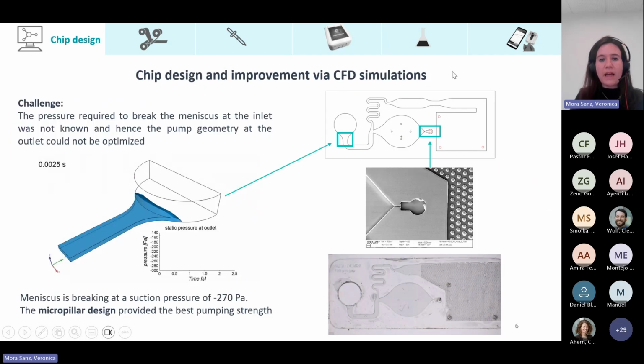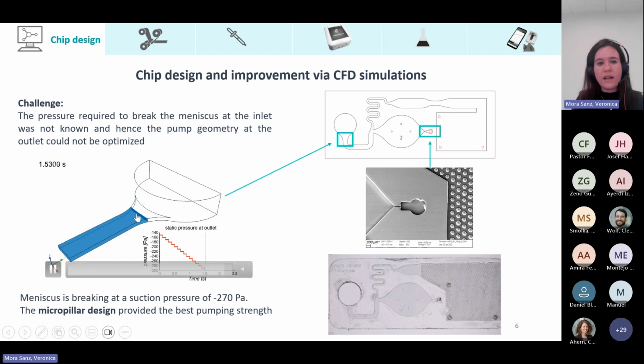Well, the chip design was improved by computational fluid dynamics simulations. To know the pressure at which the meniscus is raised was a very important parameter. And for this, here we can see a model of the inlet. Here we can see that this meniscus is formed at a pressure of minus 160 pascals. And then when we achieve a suction pressure of minus 270 pascals, the meniscus is broken and the liquid starts to flow through the chip.